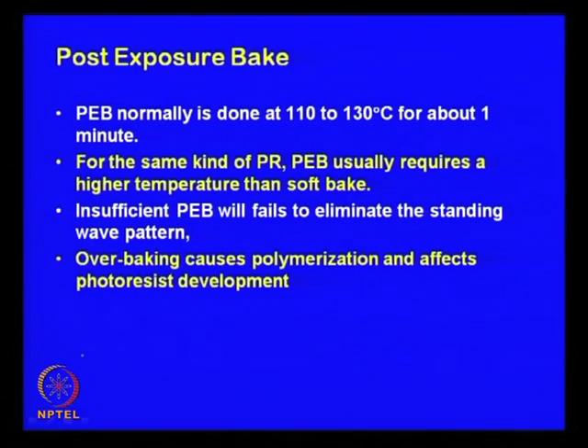So, continuing our discussion, after your exposure is over, there is a step called post exposure bake. Post exposure bake is typically done at a temperature between 110 to 130 degrees centigrade for roughly about 1 minute. And for the same photoresist, the rule of thumb is that post exposure bake is at a slightly higher temperature than soft bake. Insufficient post exposure bake will fail to eliminate the standing wave pattern.